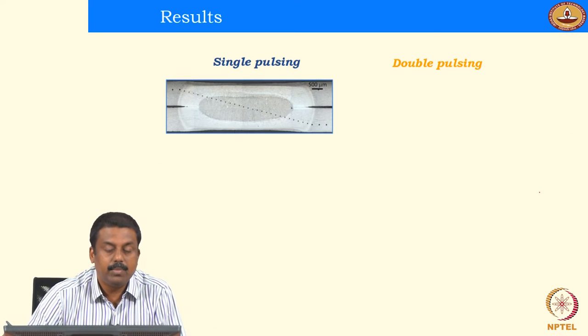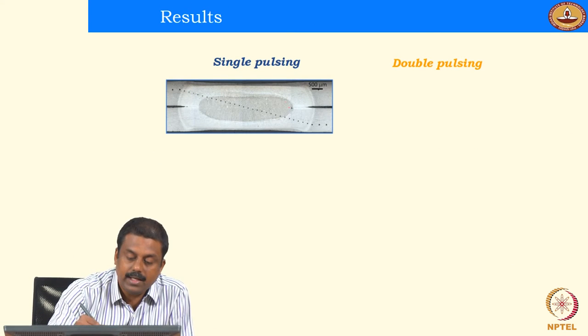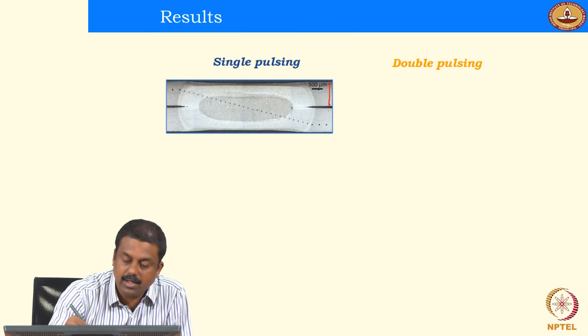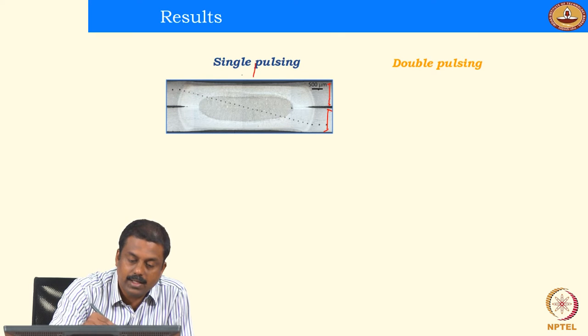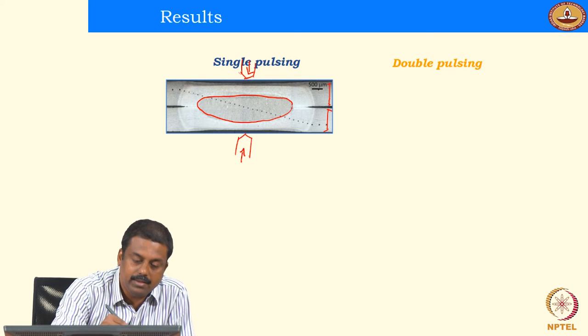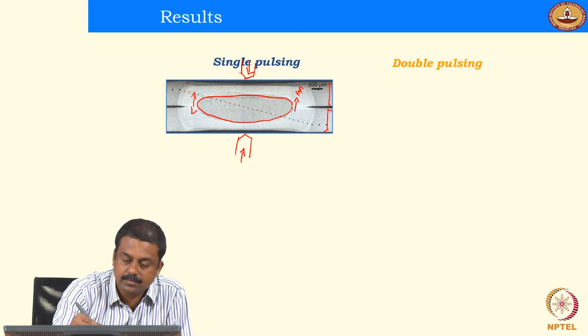So, what happens in single pulsing? In single pulsing, we generate a weld nugget. This is sheet 1, the top sheet, and this is the bottom sheet. When you are using an electrode, you pass a current and we also apply a load, and doing so we melt the interface and form what is known as the weld nugget, right? And these regions are the heat affected zone regions.